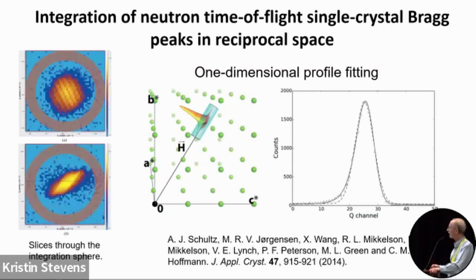And here we see for a spherical integration, this would be the background, the gray, and this would be the peak here. And this slice is kind of normal to the HKL vector, and this is along the HKL vector. And we can also fit ellipsoids to the peaks and integrate that way, which is, I think, typically what they do now. But we also found that we could do one-dimensional profile fitting.